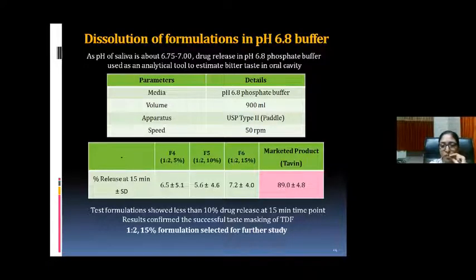And what results were found? For 1:2 with 5%, 10%, and 15%, you observe that the test formulation showed less than 10% drug release at the 15-minute time point. These results confirm successful taste masking of the TDF. That is why the 1:2 15% formulation is optimized and selected for further studies.